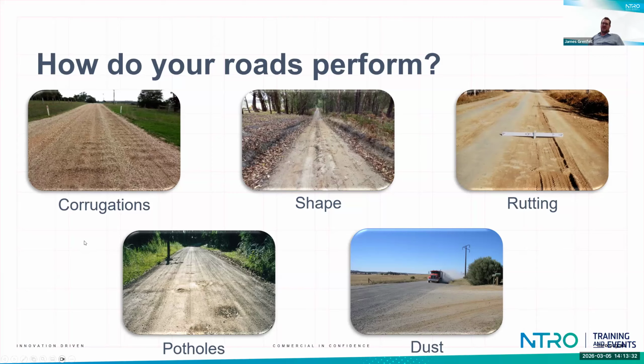The granular materials, and those materials can then be very susceptible to changes in climate conditions. Obviously, in very dry conditions, they become dusty. They could be subject to loss of material, or depending again on the materials in question, may be subject to corrugations. But obviously, if we get very wet conditions, we can have issues with potholing, with rutting. The unbound granular materials can become quite unstable under changes in moisture conditions.